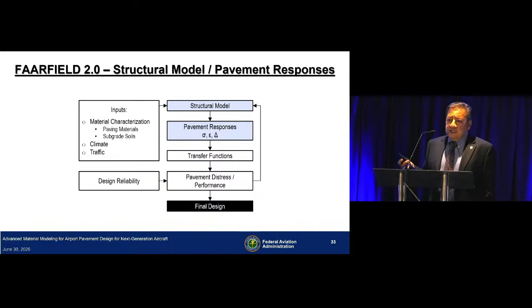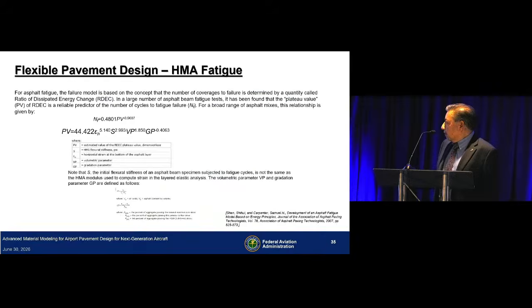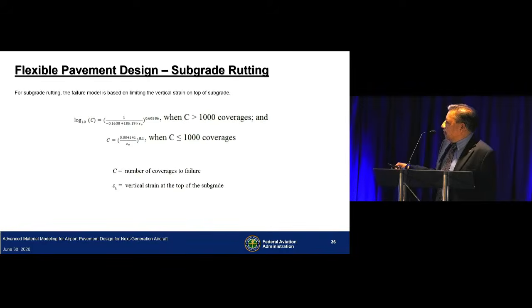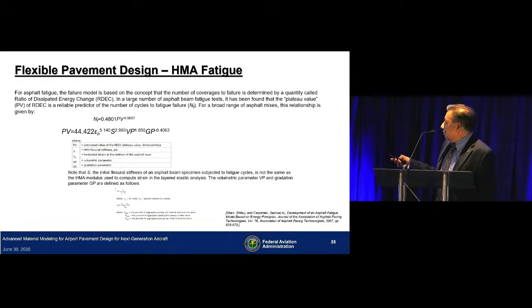Structural model, we already talked about, it's layered elastic analysis for flexible and 3D finite element for rigid. For pavement responses, we are looking at strains in the asphalt concrete and vertical strains on top of the subgrade. The failure model that is embedded in FAARFIELD is based on the ratio of dissipated energy change. This work was done at the University of Illinois by Professor Sam Carpenter and his PhD students. There is a report and paper listed at the bottom if you want more details.